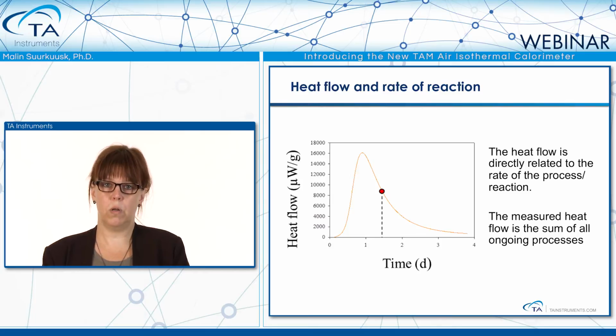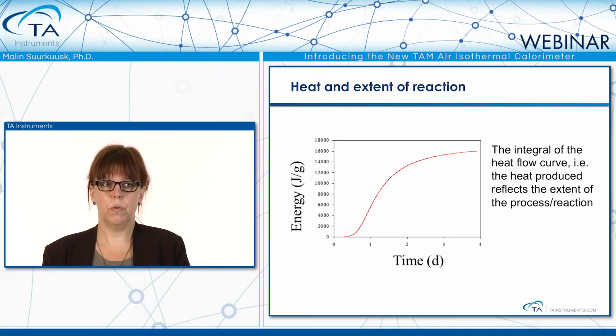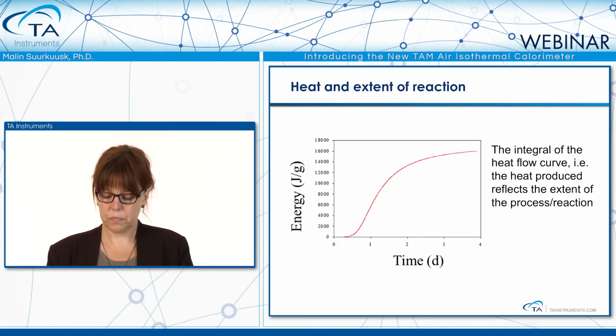So it's the sum of all the ongoing processes. If we integrate the curve, we get the heat, the total heat out of the reaction. And then if we integrate joules per second over time, we get joules. And if it's normalized, we have joules per gram, which we plot on the y-axis. And that's again plotted against time. And here, the total heat of the reaction is then related to the extent of the reaction under study.